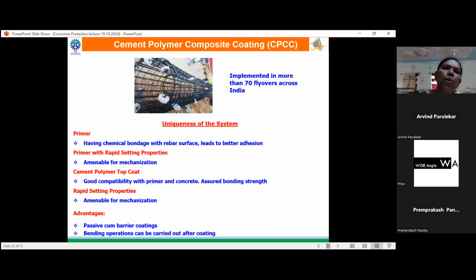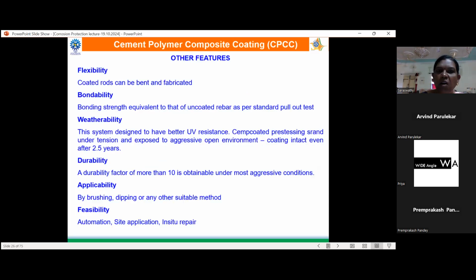So this is the improved version, the cement polymer composite coating. Here it contains cement plus polymer. The earlier system contains cement plus inhibitor, that is a water-based coating. This is a cement plus polymer coating, so it has the added advantage of flexibility. The previous coating does not have that much flexibility, but this coating does. And this system has been implemented in more than 70 flyovers across India. So it has all these characteristics and features.